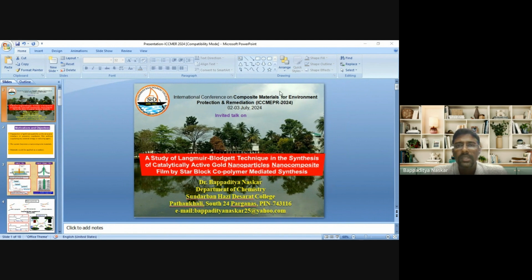And there are also possible tetra-block copolymers, which are sometimes related or close to the star type of block copolymer. They require a linker, which is actually ethylene diamine. Here we are interested to study 2 block copolymers, namely Tetronic 701 and Tetronic 90R4. Basically, they are prepared by BASF. As we see, here the PPO and PEO block ratio is different. Also, the position of the PPO block is reversed in T701 compared to T90R4.